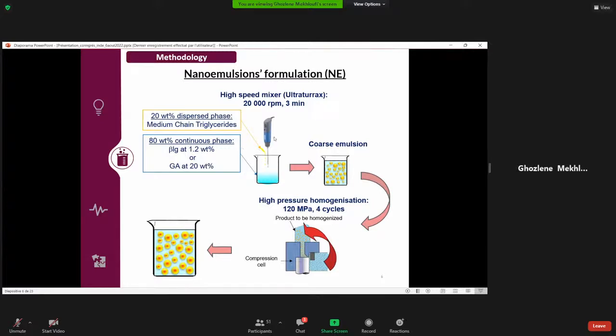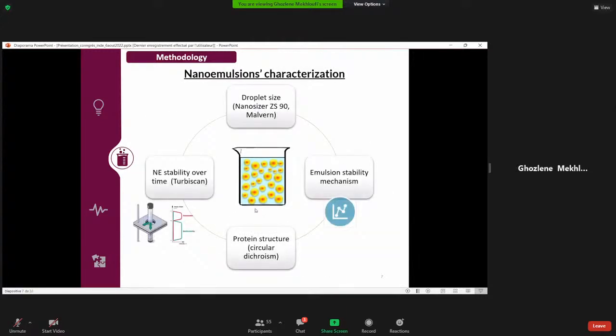So nanoemulsions were prepared by adding progressively the oily phase to the continuous phase while mixing using a high shear mixer. We obtain coarse emulsion which is immediately introduced in a high pressure homogenizer for 4 cycles, operating at a pressure of 120 megapascal. And we obtained nanoemulsions. These nanoemulsions were characterized by measuring the mean droplet size, the stability of nanoemulsions over time is followed by visual observations, by measuring the backscattered light using TurbiScan, and by measuring the mean droplet size.